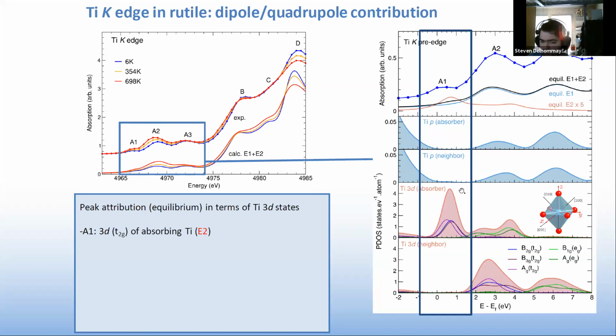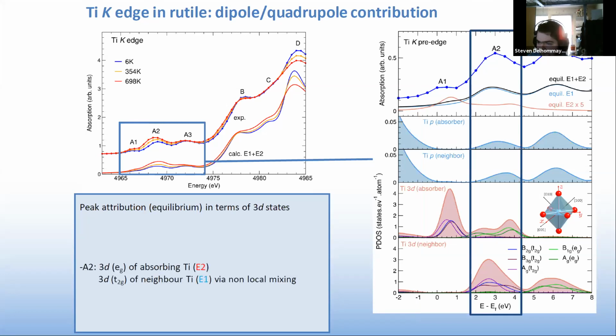This is for peak A1. I would also like to mention that, just like aluminum, you can see here the titanium site is centrosymmetric, and so we do not expect any local mixing between the P and D states. And it can be seen here. You can see there are no P states here whatsoever, at least at equilibrium. So we talked about the E1 peak. We can talk in the same way about the A2 peak.